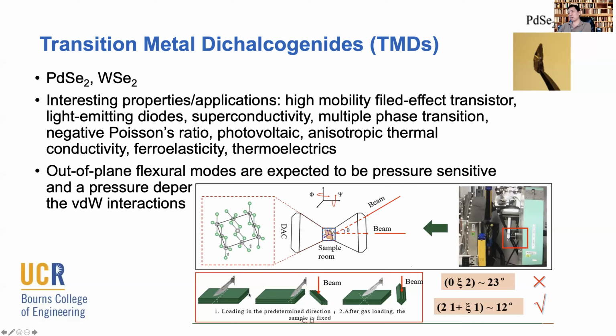That means we have to mount the sample 90 degrees from its natural loading direction. This is usually done by making a small slice of the material along one of the high symmetry lattice axes, and then we turn it 90 degrees and load it inside the diamond anvil cell. Now here comes the tricky part. This loading is very difficult, as you can imagine. Most of the time when you try to cut a very soft and delicate material like the 2D van der Waals compounds, you end up destroying the structure completely.